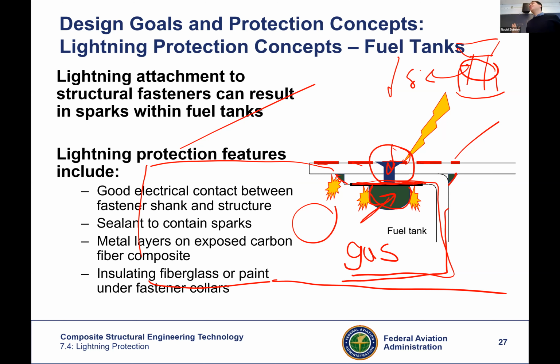So that kind of guarantees that your design of the fasteners is good, but then the quality of drilling becomes quite important as well. What I have seen is that they make coupons representing the bonding points, let's say multiple fasteners, and then take it to the lab and they test it with a fake lightning strike. And if there's any sparks in any of the fasteners, that means that you didn't certify that design. So they will go back and redesign it. And the number of fasteners, their spacing, all of that becomes key. Basically, you have to guarantee energy comes in, gets dispersed around the fasteners, doesn't go toward the gas tank, doesn't create any sparks. So it's a very detailed design.